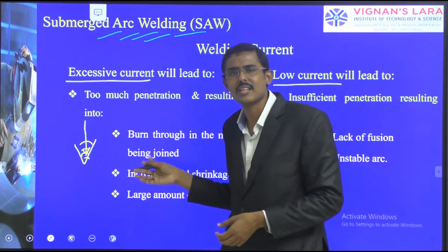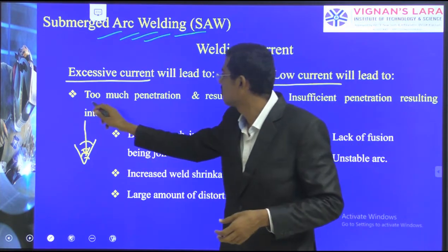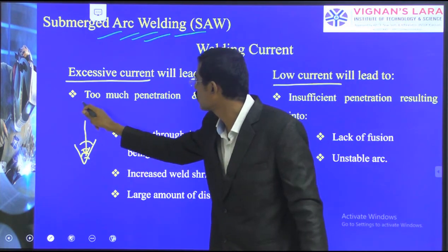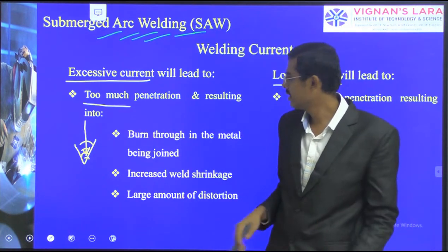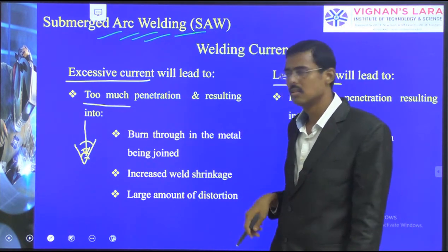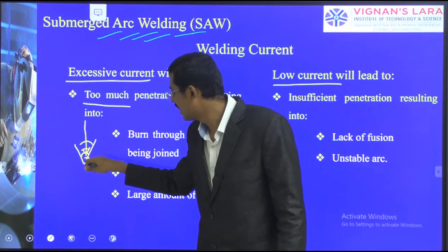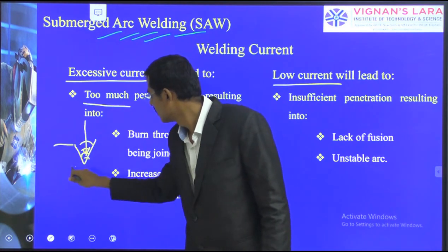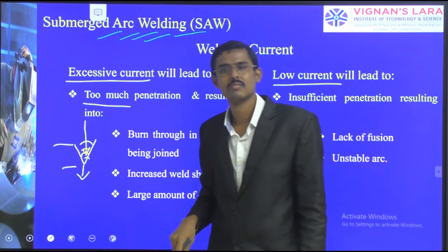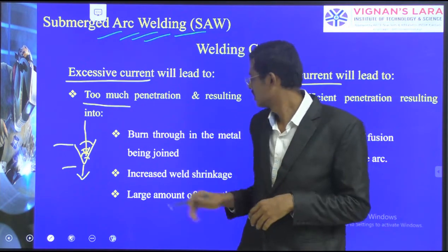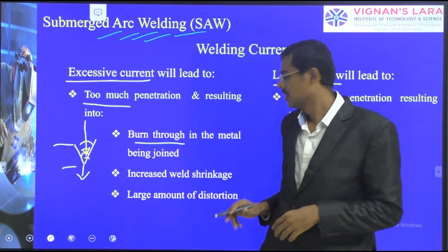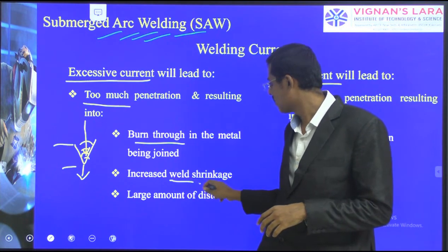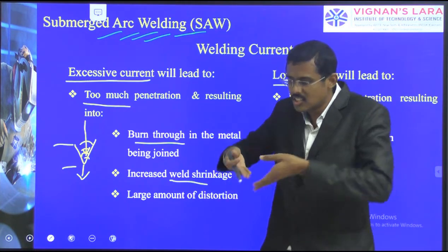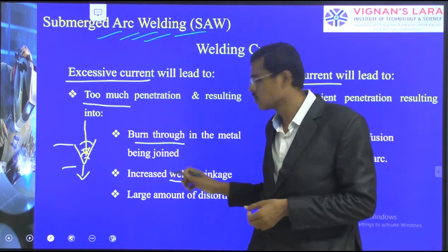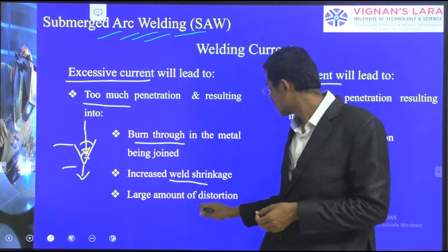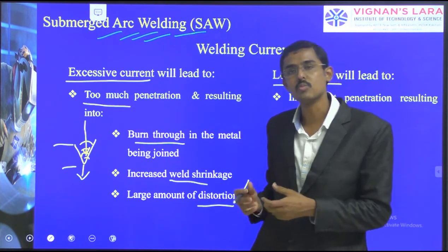But there are some other points. What happens if it is too high? We are not talking about high current, we are talking about too high current. What happens? Burn through is possible. It may come through after welding the required thickness. That is totally bad. Increased weld shrinkage: with much more heat, it shrinks and distortion will happen. That is also possible. Large amounts of distortion are possible there.